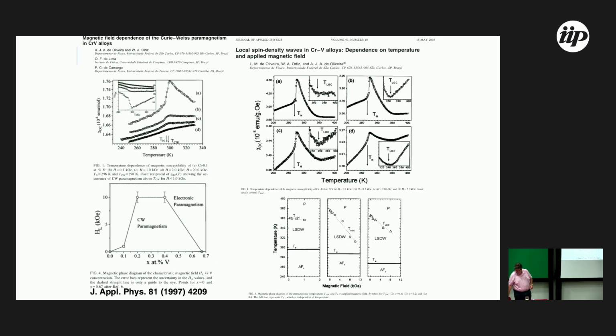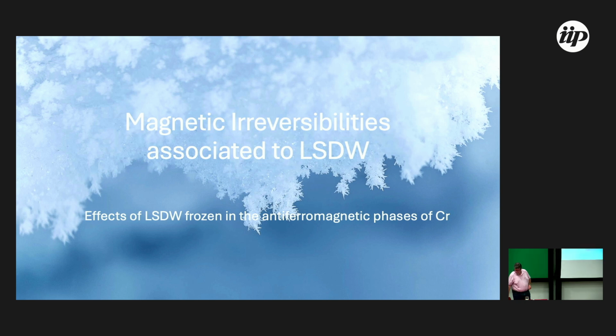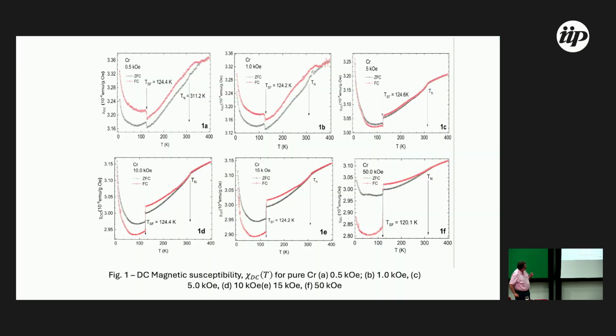These are the more important results. And as a consequence, they produce magnetic irreversibilities associated with the chromium samples. These are recent results on chromium, at different magnetic fields: 0.5, 1 kOe, 5 kOe, 10, 15, and 50 kOe. Observe the pure chromium.